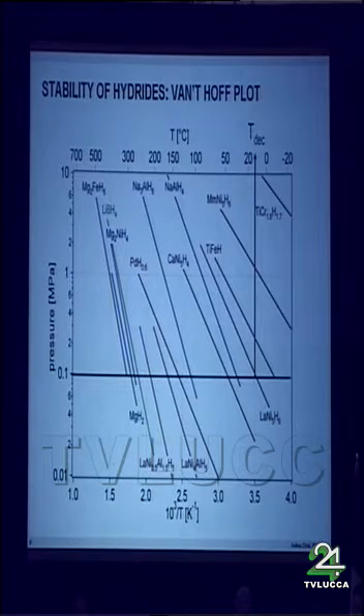Now, the Van 't Hoff equation of many systems looks like that, and you can see in general these lines all point to the same interception point on the axis, which is again the 130 joules per Kelvin mole standard entropy of hydrogen. And we have a wide range of intermetallics and metals which cover a range from something like -20 to 500 degrees centigrade at 1 bar pressure.